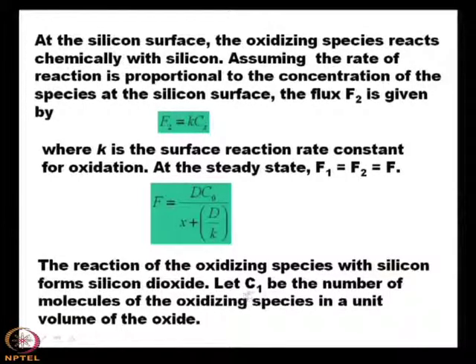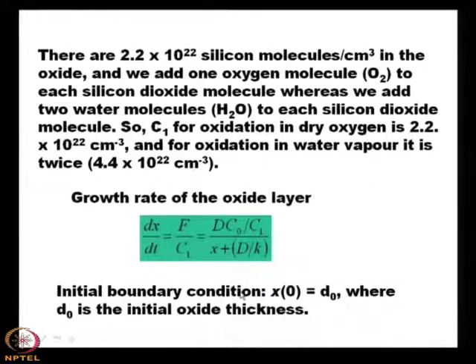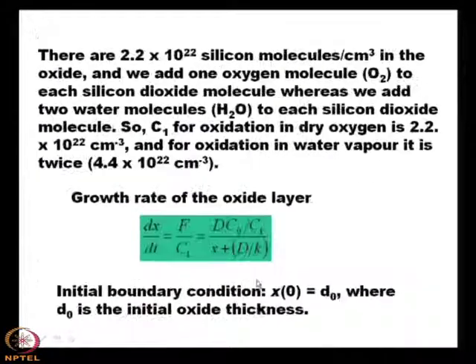Remember that this C1 we have assumed is the number of molecules of the oxidizing species in a unit volume of oxide. Then we must be interested in the value of C1. There are 2.2 × 10^22 silicon dioxide molecules per centimeter cube in the oxide, and we add one oxygen molecule to each silicon dioxide molecule, whereas we add 2 water molecules to each silicon dioxide molecule.